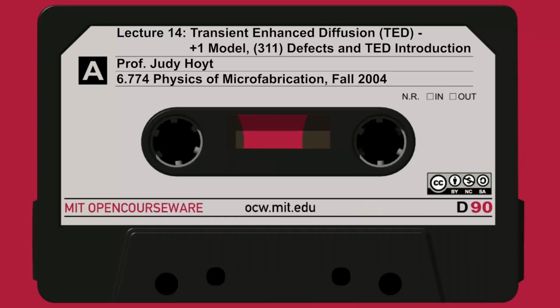Again, why do I want that? Remember in our discussion of diffusion, the diffusion coefficient goes like a diffusivity times f_I times C_I over C_I star. So whenever you enhance C_I over C_I star, you enhance the diffusivity of, say, boron. So I write down this ratio, and we have to use C_I star.